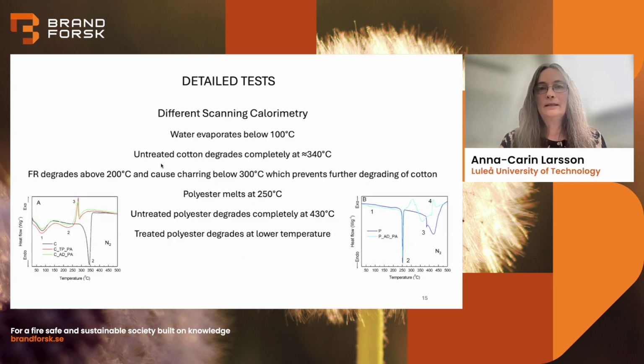With differential scanning calorimetry, we can investigate heat changes during those processes. Endothermic reactions take heat from the fire. We can see here that evaporating water is an endothermic process. Number 2 is when the flame retardant breaks down, and then we can start the charring - peak 3 is the charring mechanism. So when the surface has charred, there is nothing more happening, just a small degrading of the sample. The untreated sample then degrades completely.